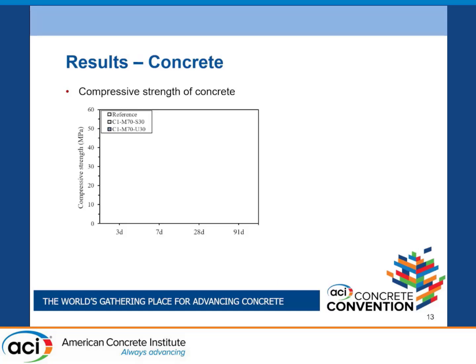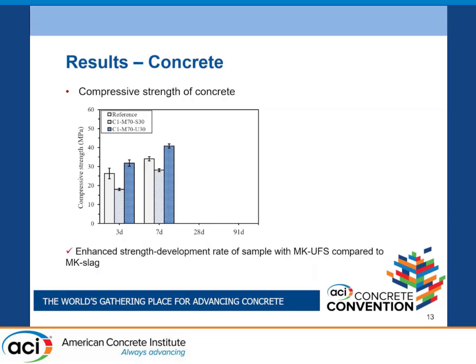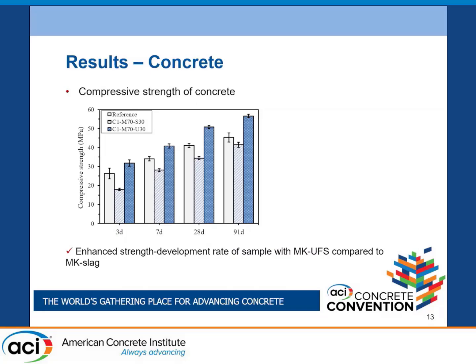The compressive strength results of the concrete: when we use only metakaolin and slag before grinding, we see a huge drop in the early age strengths. But when we are using ultrafine slag and metakaolin, as early as 3 days our compressive strength is higher than the reference. And remember that we have 58% lower Portland cement. And the strength development continued at later ages, even at 91 days, and it was about 25% higher than the reference sample.